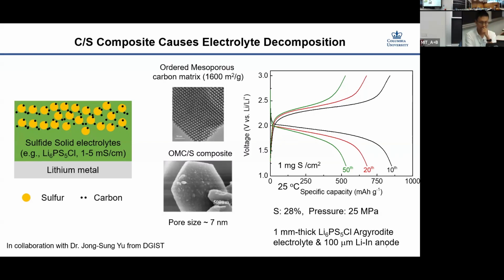No matter how we optimized the process, we always got pretty bad results. The capacity decayed from roughly 900 mAh at the 10th cycle to just a little over 550 mAh, and this is really bad performance. It wasted about half a year, and we could not figure out why. Oh, we know why. Because of the carbon's high surface area, people know that it can oxidize the sulfide electrolyte, so that we get decomposition of the solid electrolyte. But we could not find a way to solve this with the mesoporous carbon matrix.